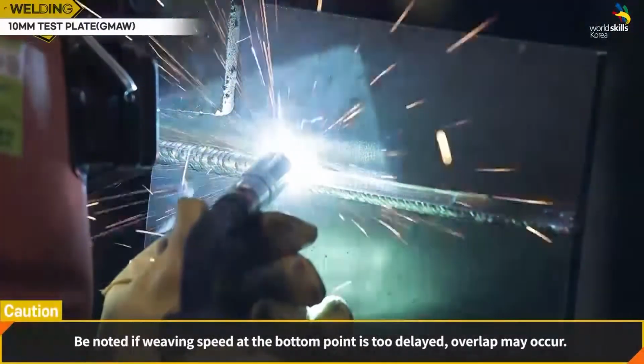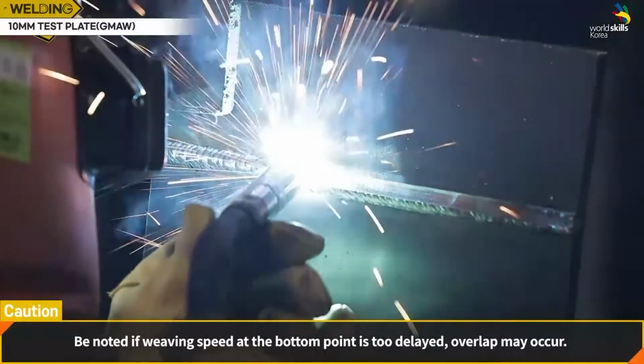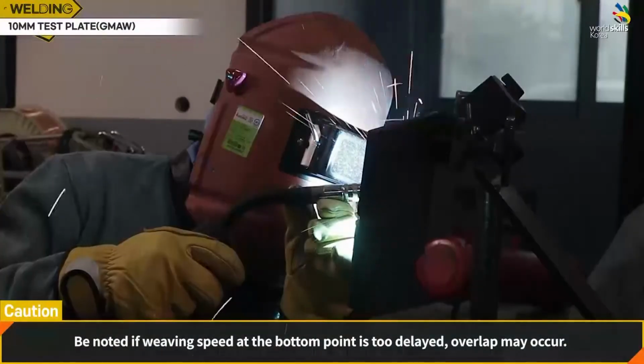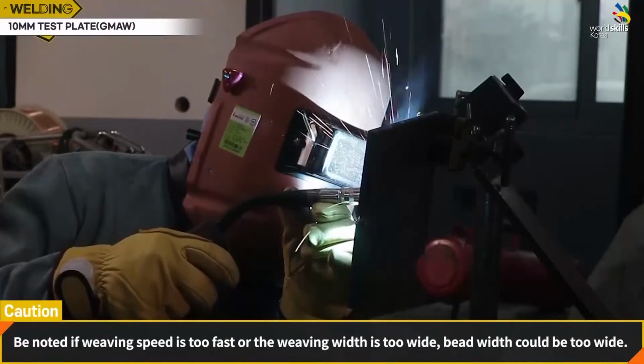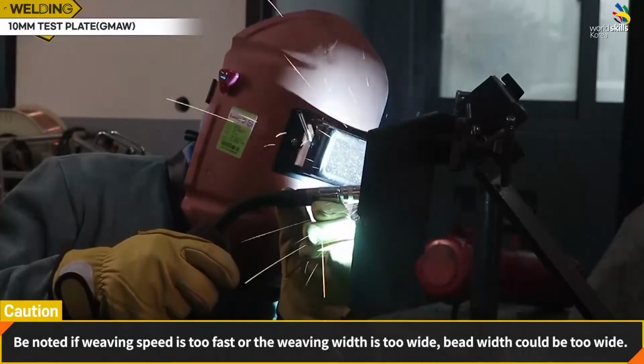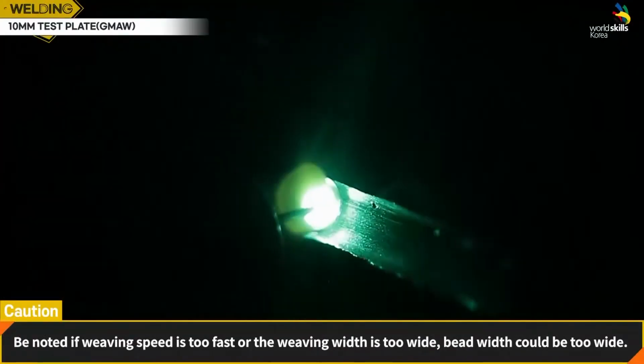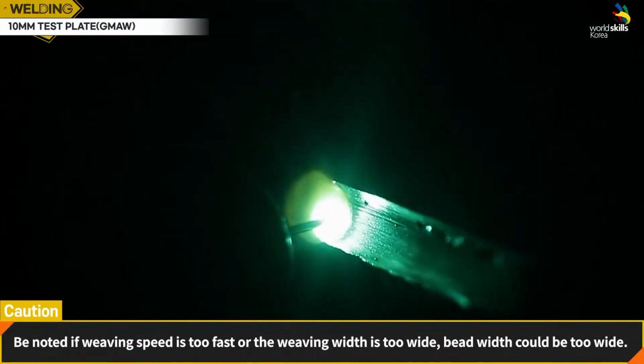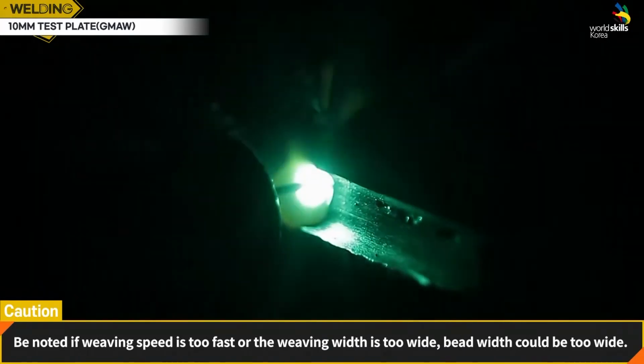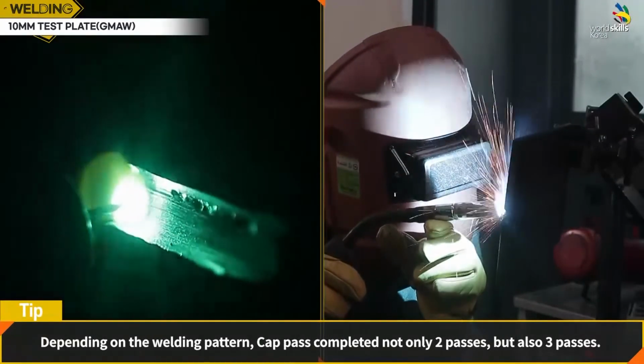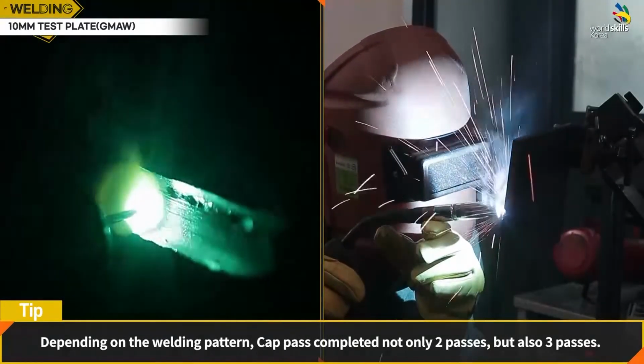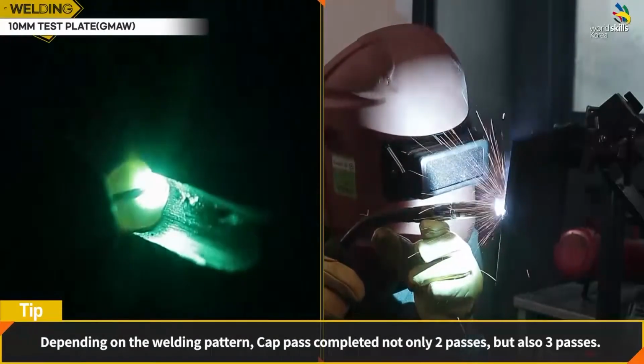Be noted, if weaving speed at the bottom point is too delayed, overlap may occur. Also, if weaving speed is too fast or the weaving width is too wide, the bead width could become too wide. Depending on the welding pattern, the cap pass can be completed with not only 2 passes but also 3 passes.